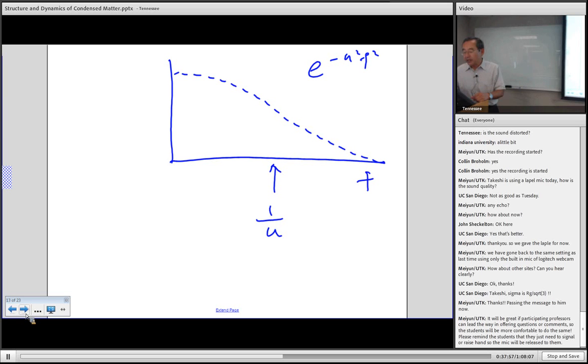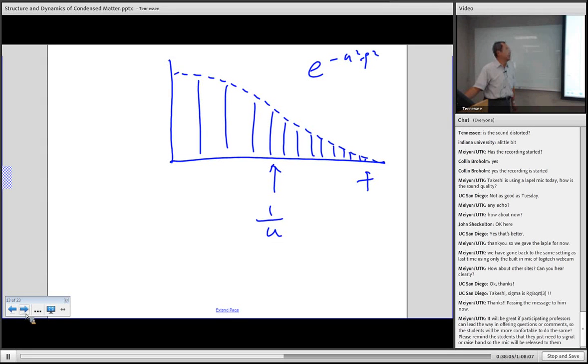And diffraction peaks appear as before. So what happens is that you have lots of diffraction peaks, but the intensity is modulated by this envelope, right? So if the position of the atom is static, you have a series of Bragg peaks forever. But intensity goes down if the atom is not static, but moving a little bit. And that is the Debye-Waller factor.